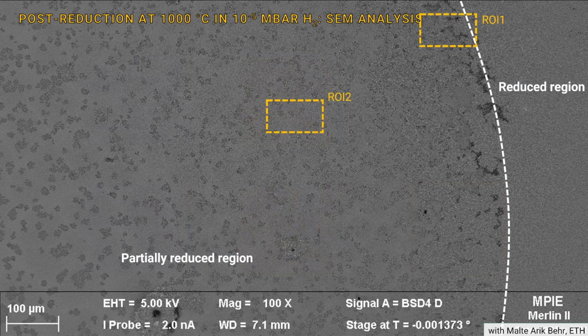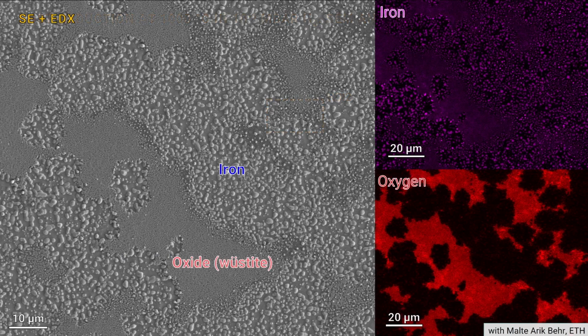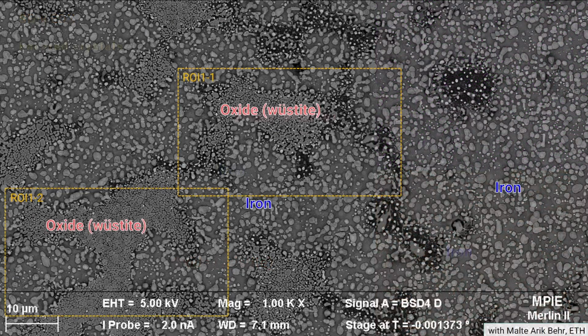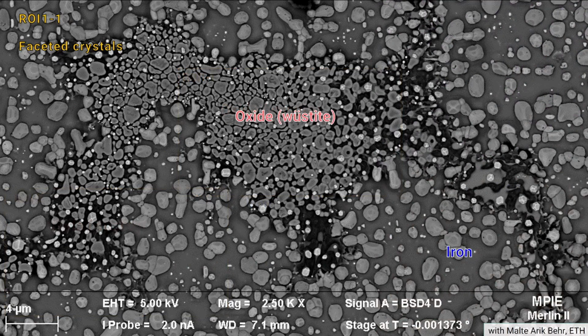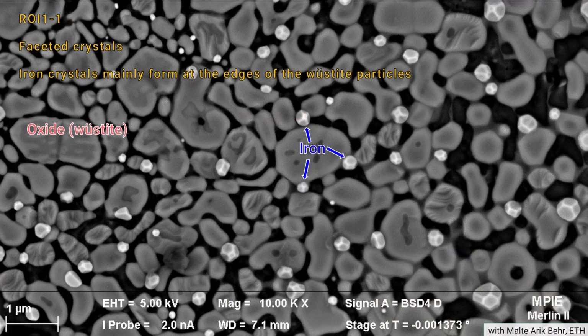Now the next step, this is again a collaboration with the colleagues at the ETH, here with Malte Arik Behr in Zurich, and we now try to study these things also in quasi two-dimensional wüstite films, which we again subject in situ to a hydrogen atmosphere, and then we study how the iron is really forming between the different wüstite layers. And that under reduced dimensions, in quasi 2 dimensions. Here you see how these very beautiful shapes of the iron nuclei are forming.